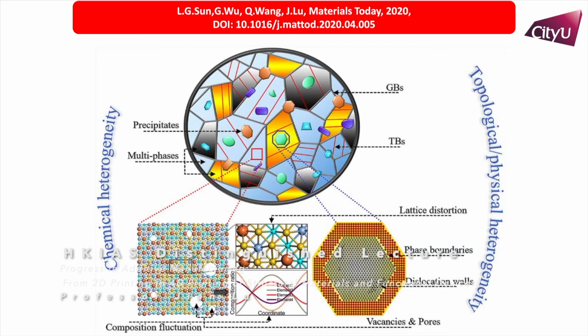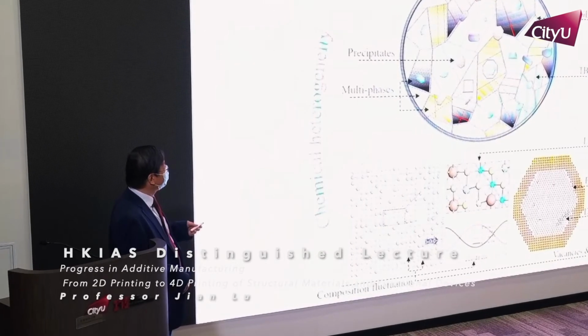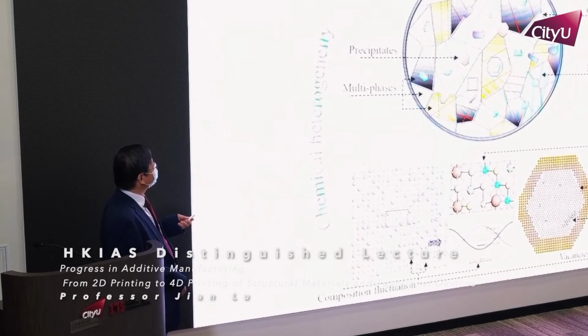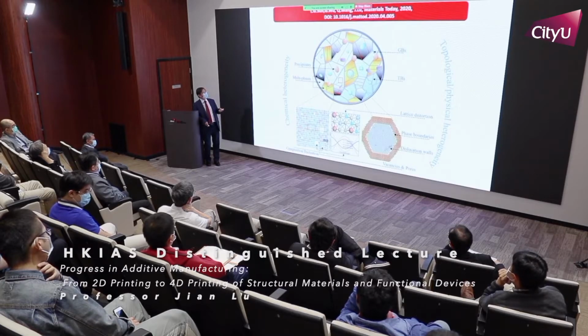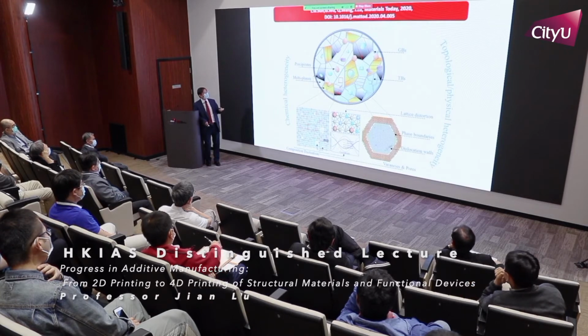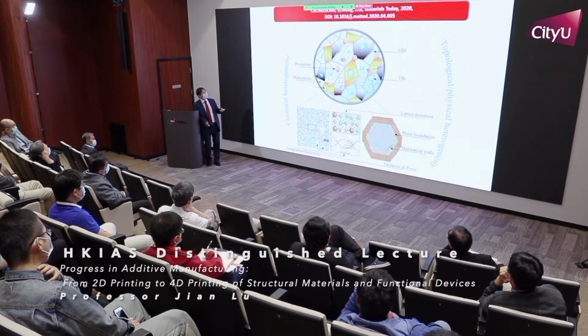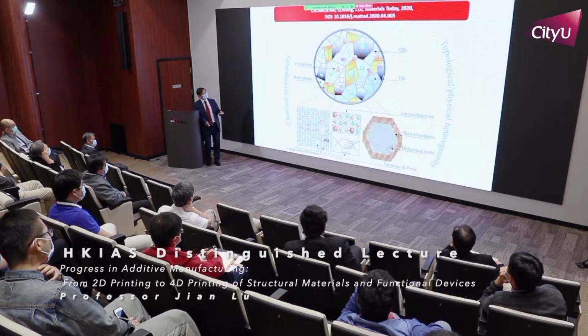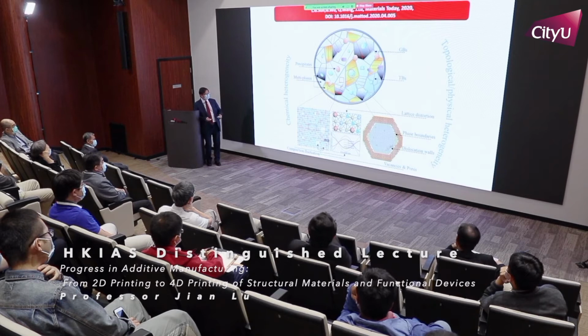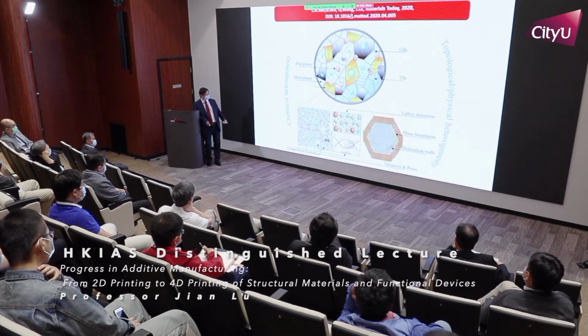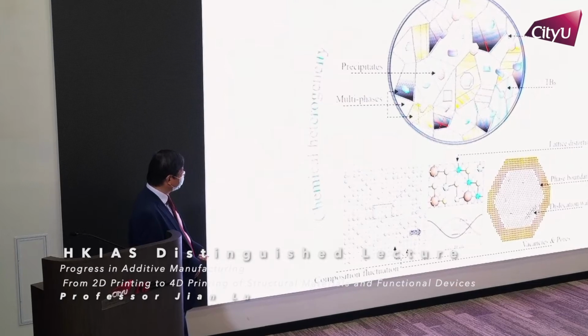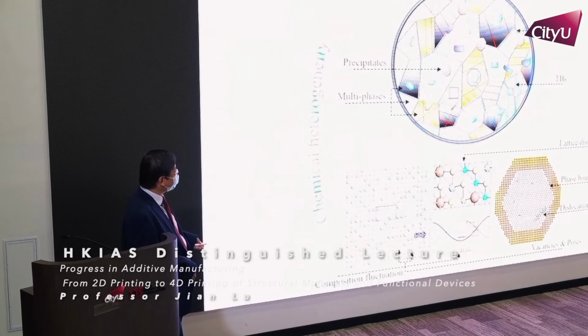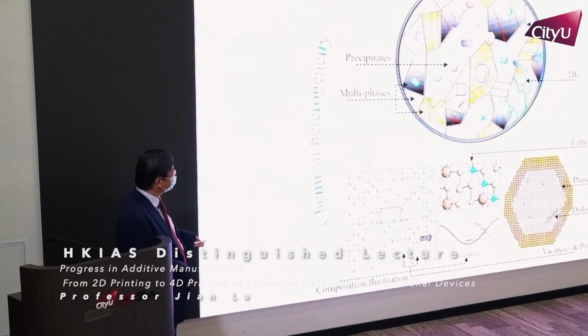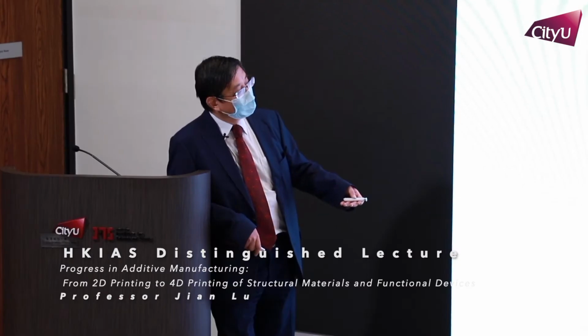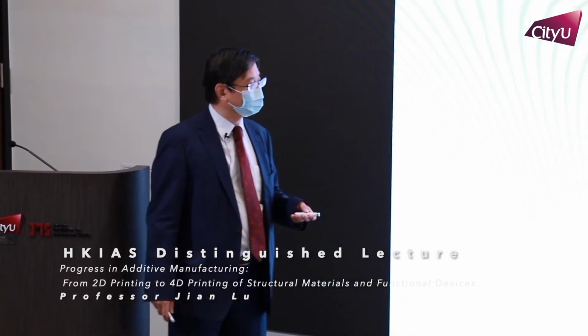Okay? So what we know in the past in material science, particularly for the metallic material, so we can generate precipitate, and with nanotechnology we generate precipitate at the nano level. Another issue is multi-phase, grain boundary, twin boundary. Okay. Then if we go down to another scale at the atomic level, we can generate composition fluctuation, okay, such as high entropy alloy. So we can easily generate this kind of distortion, and also we have lattice distortion.